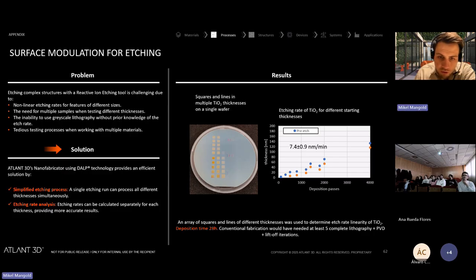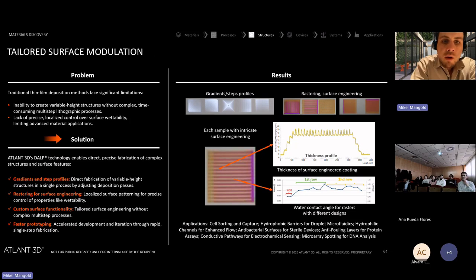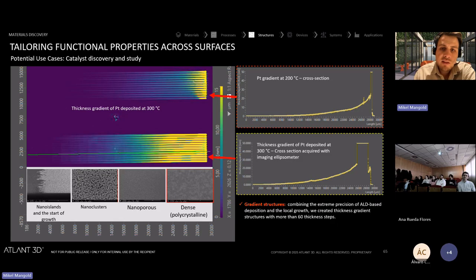If we look now at this one, as I mentioned, we can fully control the height of the deposition. So by controlling the thickness, we were able to create modulation of a surface, and that created, if I'm correct, hydrophobicity. That is something that we use as a protective layer on our device, like some hydrophobic coating, and so on.